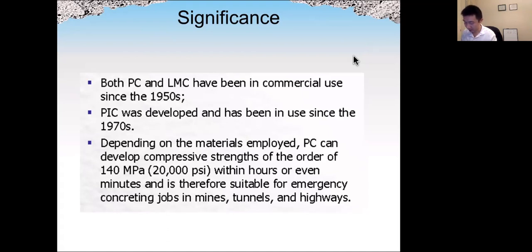For polymer impregnated concrete, we use the polymer to seal the micro cracks and also the pores inside existing concrete. If we feel the existing concrete is weaker and less durable, we may want to use polymer to seal these cracks and pores. It can achieve very low permeability in the concrete. And because the procedure to apply the polymer in PIC is kind of tedious, we normally use that in a precast plant.